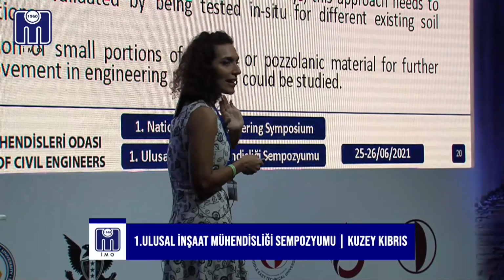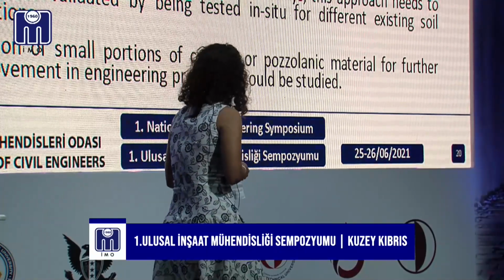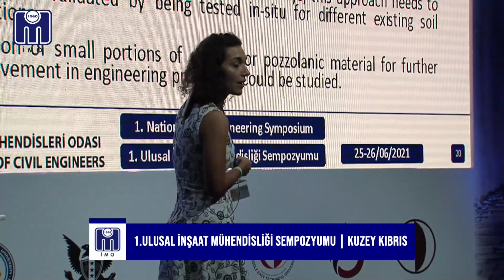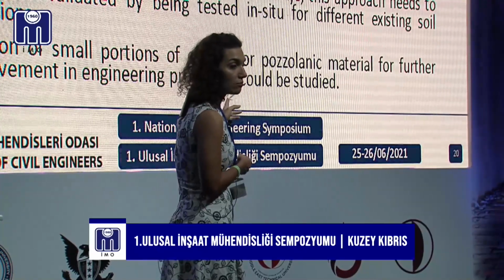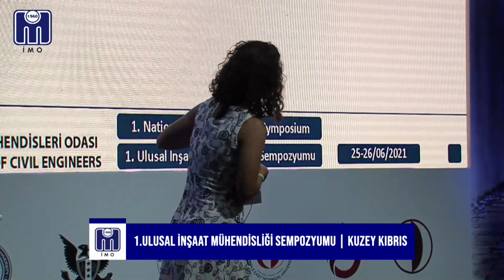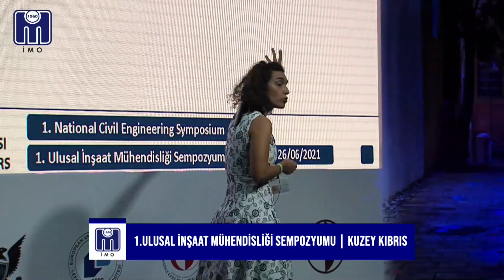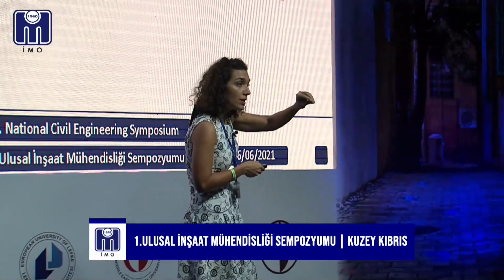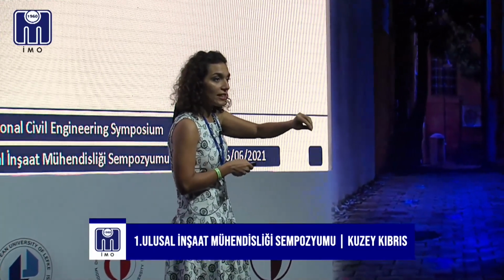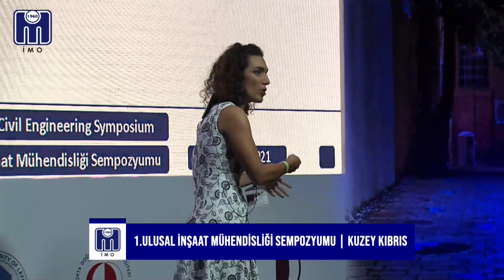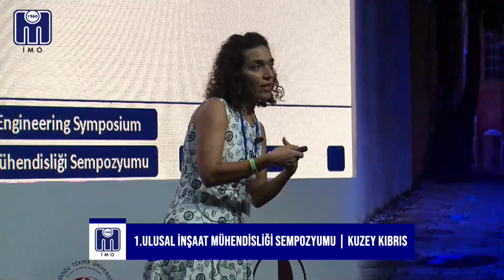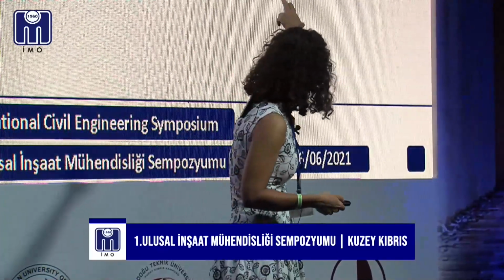So again, we did the CBR as well. A higher CBR will be achieved by a higher content of plastic. So here, if we want to use an optimum number for the plastic to have the maximum dry density, yet to have a good strength, we would be talking about 0.3%.